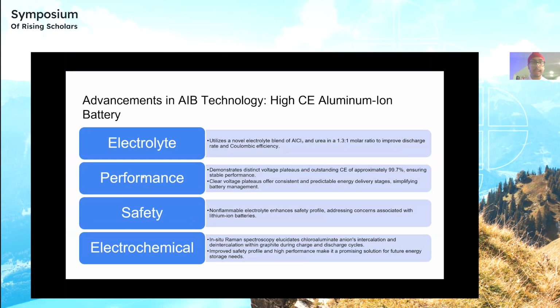Another battery technology is the high Coulombic efficiency aluminum-ion battery. It has a really proprietary blend of the electrolyte of aluminum chloride in a 1.3 to 1 molar ratio to improve discharge rate and Coulombic efficiency.